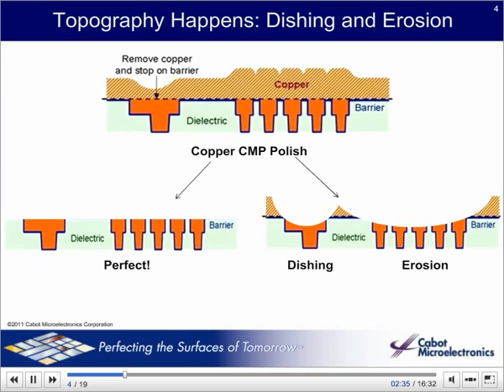In an array of fine lines, the composite effect is similar. The greater local mechanical forces on the narrow oxide lines that stick out after the copper dishes causes them to abrade faster, and we get erosion through a similar process as dishing. Sometimes dishing and erosion can remove so much of the metal that the final electrical resistance of the circuit becomes too great. Also, as the next layers are placed on top of the dish surface, it may be difficult to get perfect alignment and the connections will be missed. Usually, the ideal state after CMP is the one pictured on the left, but it rarely happens that way.